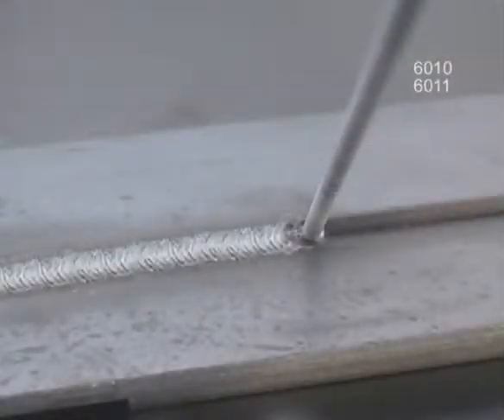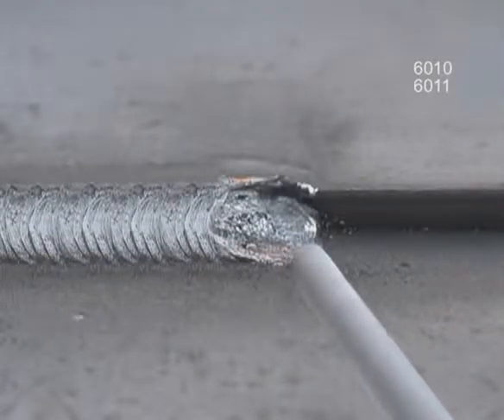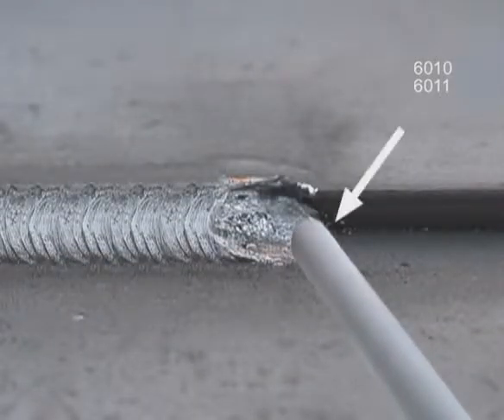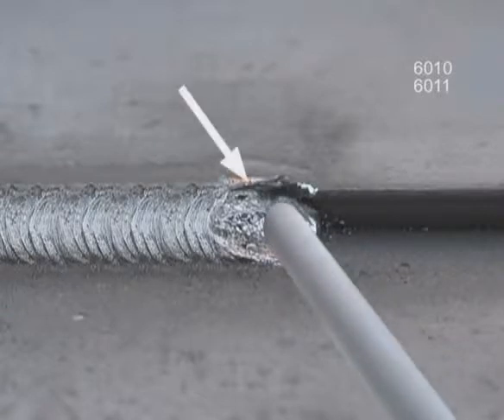With 60-10 or 60-11, hold the rod nearly perpendicular to the weld. With the arc on the leading edge, move the puddle into the bottom corner. Push it up to the top edge and bring the rod around to the leading edge. You may need to speed up or slow down to provide the heat, but always bring the arc back to the leading edge to fuse the corner. Watch the puddle flowing out to the top edge and tying in on the bottom.